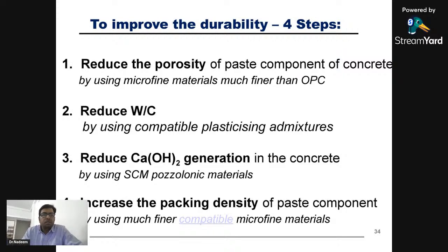Of course, reduce the water cement ratio. Reduce the calcium hydroxide generation by utilizing that compound with SCM. With the pozzolanic action, the pozzolanic material reacts with calcium hydroxide and converts it again into CSH gel. And of course, increase the packing density of the paste component, because the cementitious material has certain sizes and also a lot of porosity, which we need to fill with the finer material. So these are the four basic steps to improve the durability.